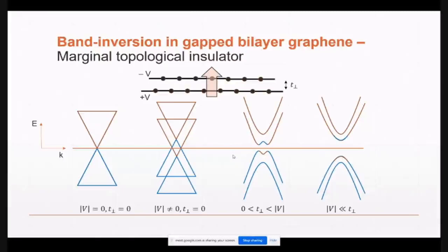The answer is no. There it is strong spin orbit interaction, which leads to the band inversion, right? And that protects the states topologically against any form of spin scattering. Standard disorder will be essentially bypassed. So those states are protected against charge disorder, but if you put in spin impurities, the protection is gone. So there the protection is by spin orbit interaction. Here the protection is layer valley interaction of some form.